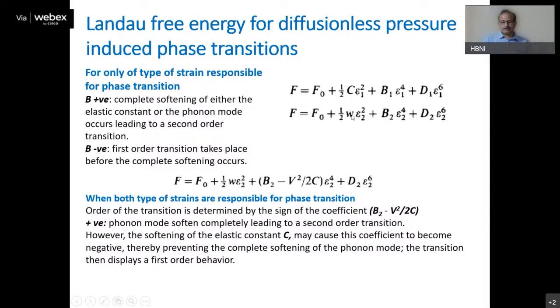Whereas when you have only shuffle strain, again when B2 is negative, it is a first order phase transition. But when B2 is positive, then this has to soften. So your phonon mode corresponding to shuffles needs to be softened. Then we get the second order phase transition.